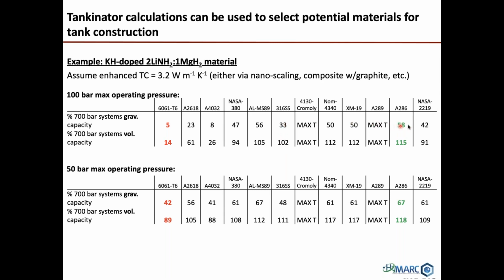Alternatively, we can make a pretty darn good improvement in the gravimetric capacity, and we can improve the volumetric if we go to this A286 alloy. This is actually a steel, not an aluminum alloy, I believe. Even better, if we could drop this pressure to 50 bar. So in other words, operate under conditions where the thermodynamics and the kinetics are good enough that you don't need to heat it so much, you don't need so much high pressure to drive the reaction. Then we can make even bigger improvements. So everything does improve under those circumstances, but you'll see that the best is still this A286 alloy.